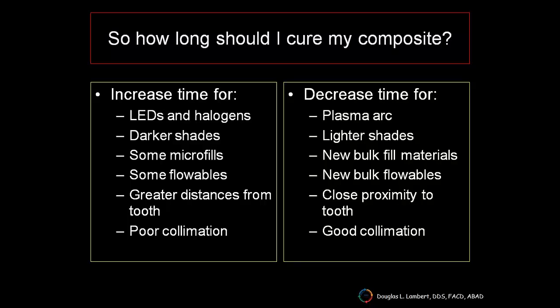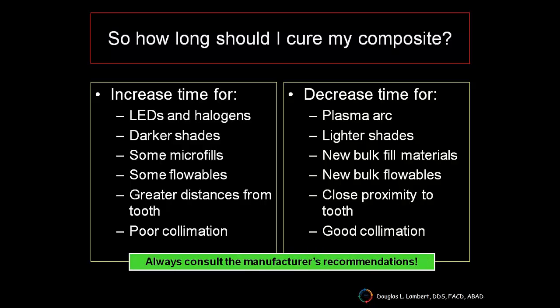On the flip side, you may be able to decrease the curing time if you're using a plasma arc light, if you've got a lighter shaded composite. Many of the new bulk fill and new bulk fill flowables allow us to cut down on the amount of time it takes to cure our materials. If we have close proximity to the tooth in the prep with the light, such as shining the light through the tooth structure, that may be helpful in potentially decreasing our time for light exposure, and good collimation. Bottom line on this is always consult the manufacturer's recommendations. I don't think you could ever go wrong if you do that.